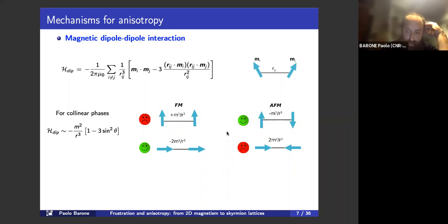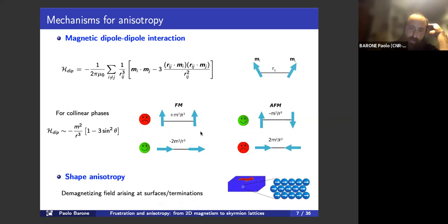And a related mechanism that also has been touched upon in the previous talk is the shape anisotropy, which is basically related to the effect of the demagnetizing field arising at the surface of the sample. But it's important to notice that this dipole-dipole interaction, even though in principle it should imply that any magnetic system has a low temperature long range order, even in 2 dimensions, has an energy scale which is very, very small. It's of the order of millikelvin. So it's 3 to 4 orders of magnitude smaller than exchange interaction. So that means that one could theoretically have a transition, but it's a ridiculously small critical temperature.